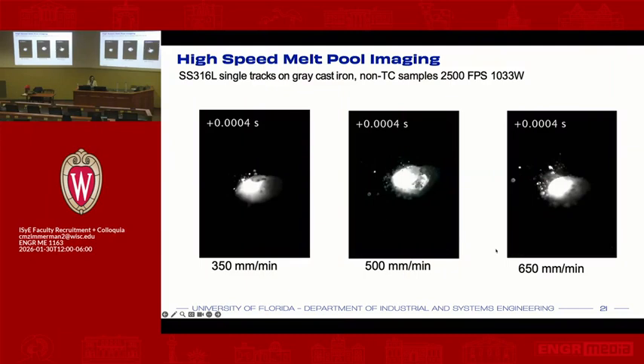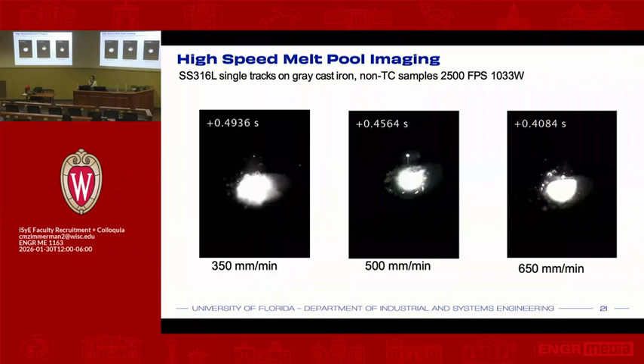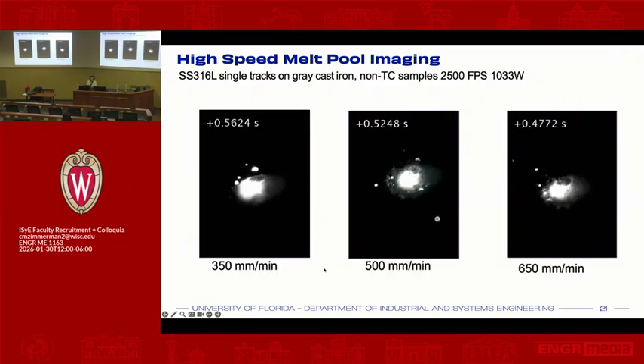Why did we see that porosity? So I have a few videos here to show you. And what you're going to be noticing is that when you actually change the speed, you can see that in this melt pool situation, the higher you go in speed, and these are basically without heat treatment, you can see a more stable melt pool, having less satellites just going throughout. And with the very, very slower type of melt pool, what you're seeing there is just a lot of bubbling. There's a lot of gas escaping from the melt pool, and there's other ones that are getting trapped, and they're getting larger porosity associated with it.